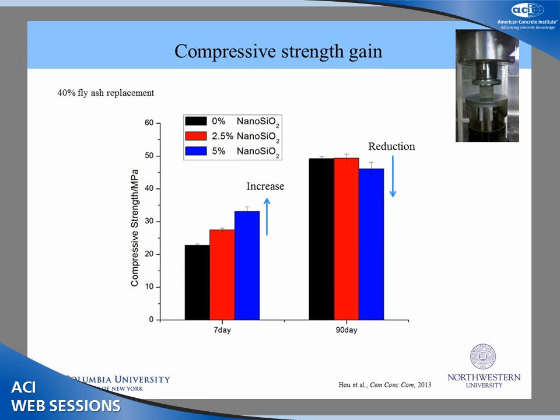So this is a compressive strength gain of 40% fly ash cement mortar with 0, 2.5, and 5% nanosilica addition. Now at the early age, we see that with increasing addition of nanosilica, there's an increase in compressive strength. This is at 7 days. So it's effective in improving the early age properties. Because fly ash, although it can introduce advantages in the long term, at the early age, there's some delay in setting, delay in early age strength gain, and also delay in rate of hydration. So here we're seeing that the nanosilica is helping to offset those negative effects.